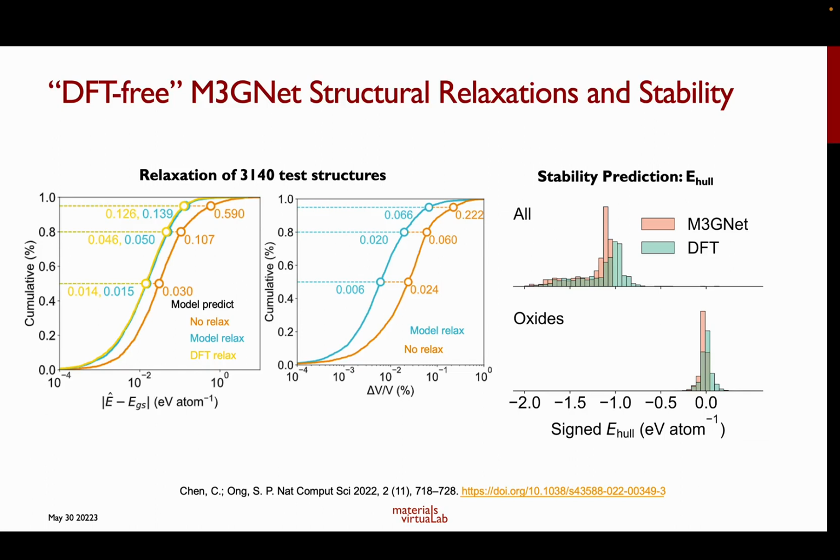energies, and stability. So if you remember, most of the properties that we are interested in for a battery are all related to the energy somewhat, right? So we can actually get the energy to within about 15 to 50 meV per atom of the ground state, okay? So this is already quite reasonable. We can already make good structure stability predictions from it.